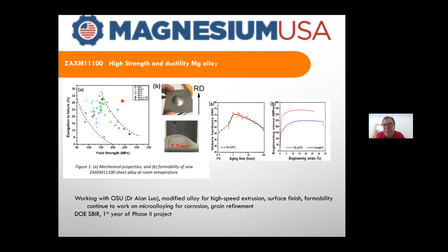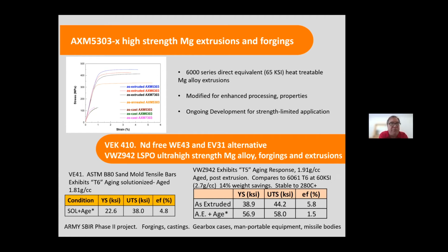So it has after heat treatment, it's very processable as homogenized, but after heat treatment, this is a 280 megapascal yield, 340, 350 megapascal ultimate with over 20%, up to 30% engineering strain to failure. And this is specifically engineered for formability and for crash energy management and energy management in automotive and transportation structures. Another alloy that we are now offering is a 6000 series direct equivalent, 65 KSI, magnesium, aluminum, calcium, manganese alloy that is low in cost, has really tremendous properties, 65 KSI, 450 megapascal strength. And again, we've been modifying existing alloys for processability.